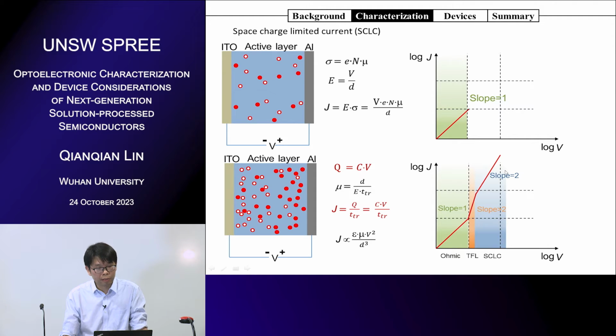From the steady state measurement, we can get IV or JV curves. And from the JV curves, we get two regions, and from these regions, we can extract the trap density and also the mobility, because we know the charge Q is equal to the product of capacitance and voltage. So we know Q, and if we know the current density, then we can extract the transit time indirectly from Q divided by J. Then we know the transit time.